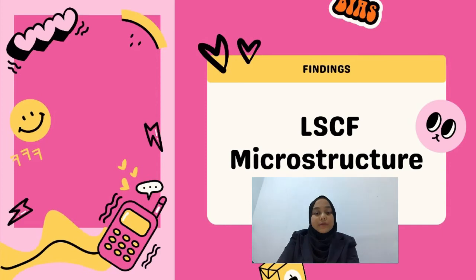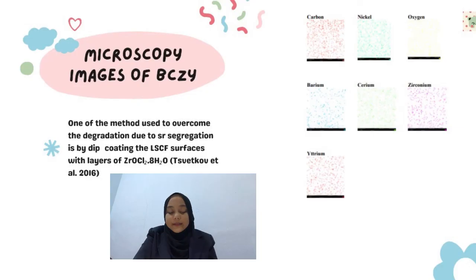The next part in the findings is the LSCF microstructure by using SEM-EDX. One of the methods used to overcome the degradations due to strontium segregation is by dip coating of LSCF surface with layers of ZrOCl2 8H2O. This cathode microstructure is still preserved after the surface modification process.